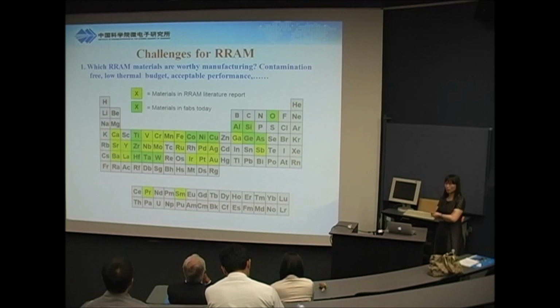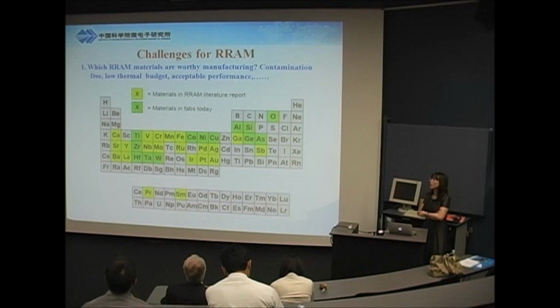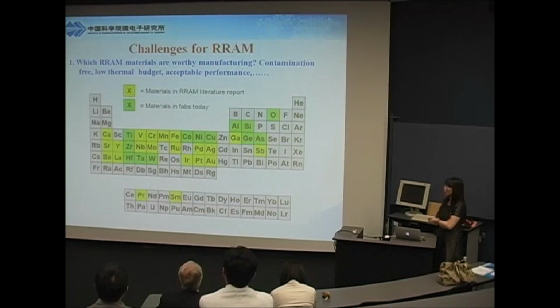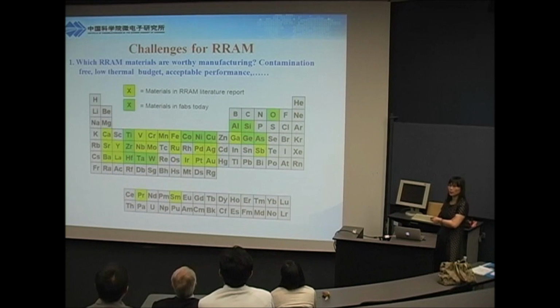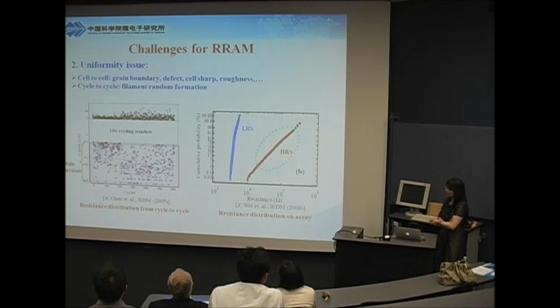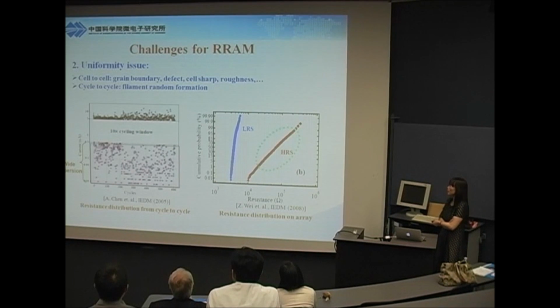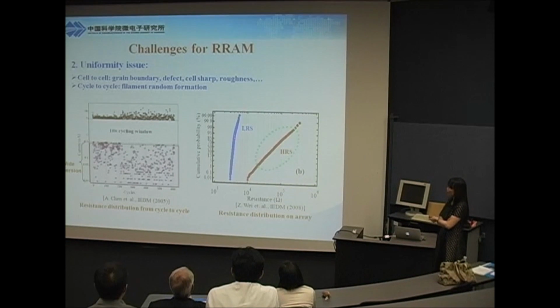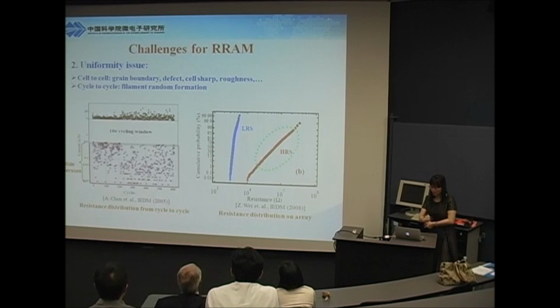But there are still a lot of challenges for this technology in real applications. First, many materials demonstrate RRAM phenomena, but this is both an advantage and a big challenge. Usually the CMOS technology doesn't like so many materials, because of contamination. If we cannot fix one material, it cannot get real application. This is one challenge. Another is that they still have a large variation in their parameters. You can see the low resistance state is more uniform, but the high resistance state has such a large distribution. This is not good for real applications.